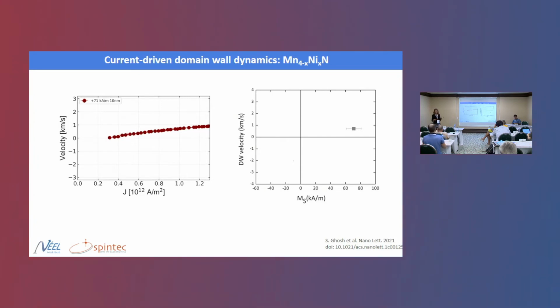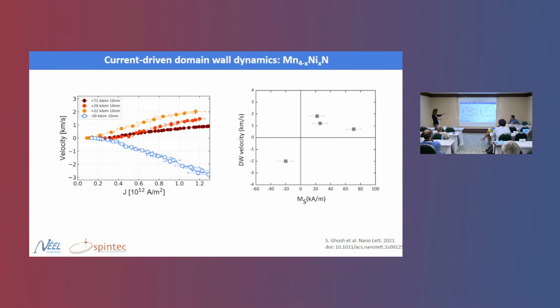But as I say, when we dope these samples with nickel, then we can decrease further the magnetization and go towards the compensation. So let's see what happens when we increase the nickel doping. This is the sample without doping, and this is again velocity versus current density. Now we start doping the sample, and I present here the velocity for this current density as a function of magnetization. So we go closer to the magnetic compensation. We keep doping the sample, increasing the nickel concentration. And then once we cross the magnetic compensation, we have a change of the direction of motion of the domain walls. And then, okay, we go further, and then we decrease again.